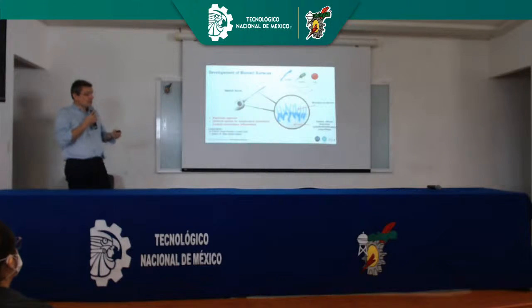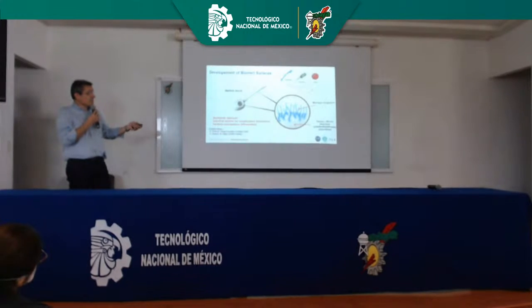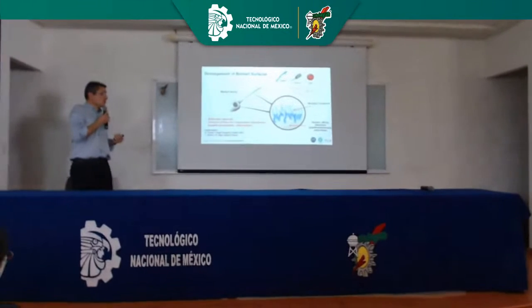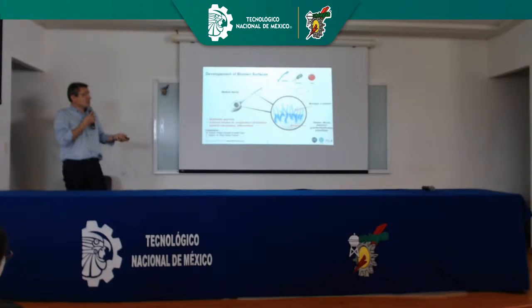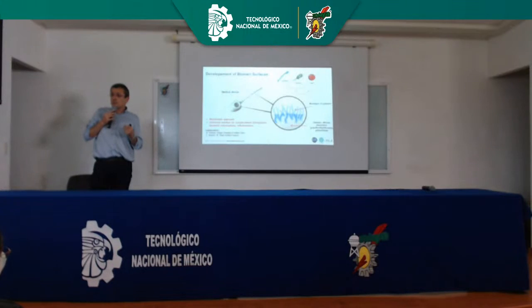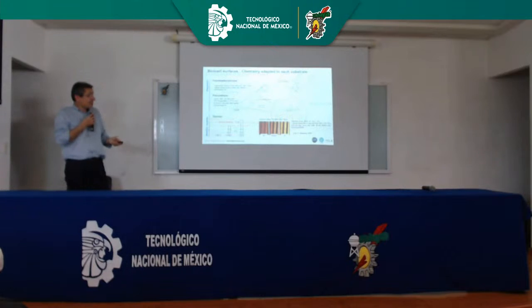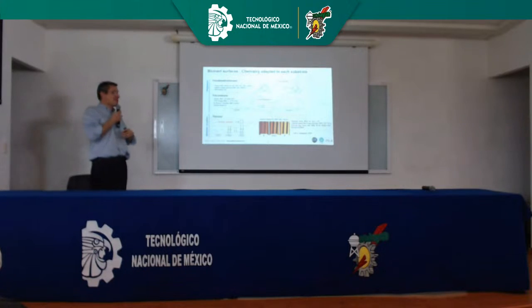How to get rid of this complication is to avoid any kind of interaction between all those entities with the material. So the idea is to suppress typically hydrophobic interaction between those two components. And to do so, it's possible to avoid those interactions by creating monolayers of polymers. Not any kind of polymer. To avoid this interaction, you need to immobilize a dense layer of hydrophilic polymers, like polyethylene glycol, polysaccharides, for example.